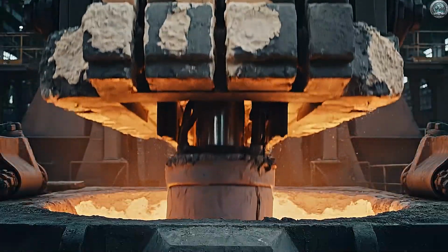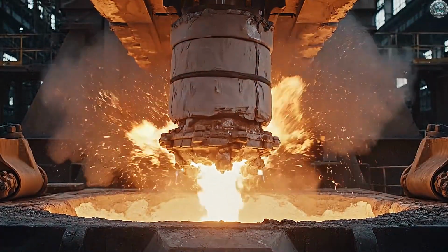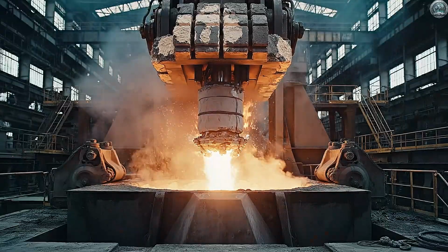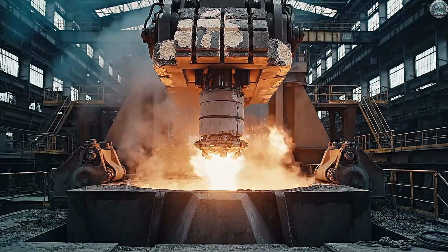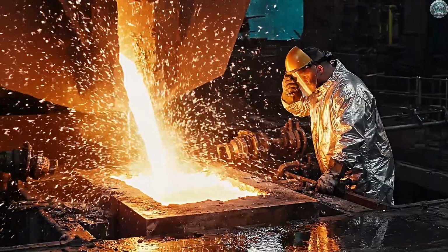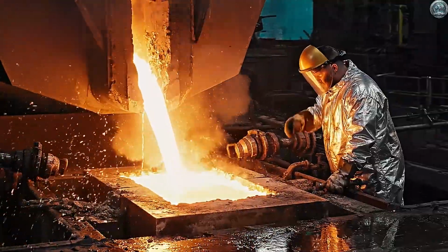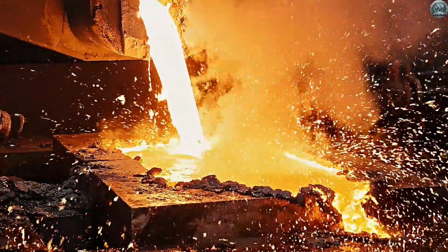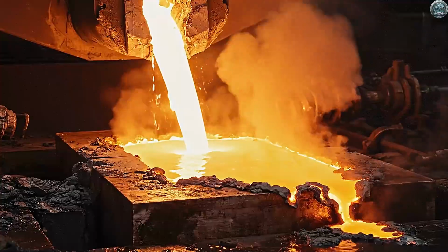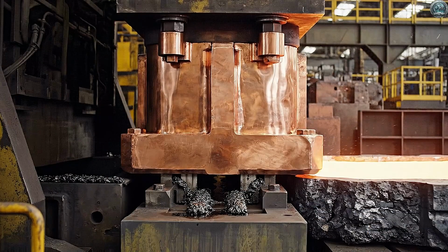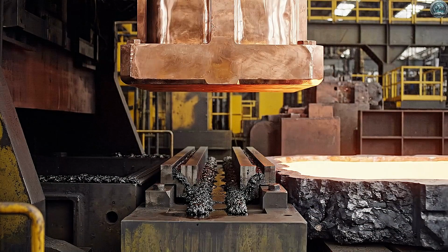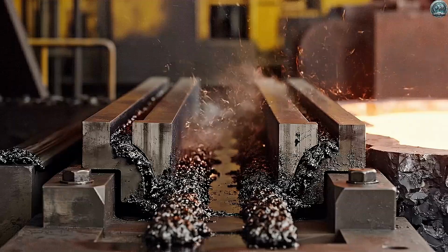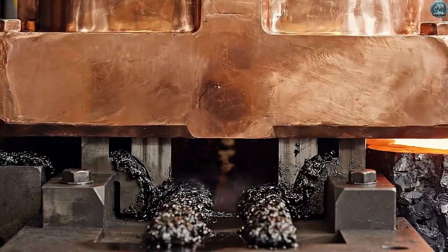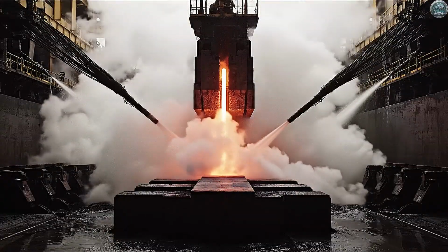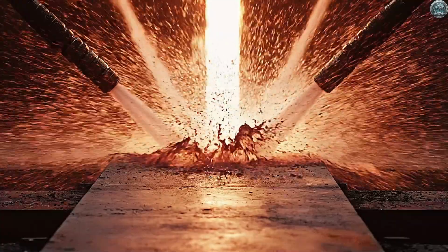Protected from the air, liquid steel flows invisibly into the tundish, a reservoir that feeds the molds. From the tundish, the steel is distributed into multiple strands, beginning its transition to solid form. Copper molds oscillate rapidly, a mechanical heartbeat that prevents the steel from sticking to the walls. High-pressure water sprays hit the emerging strand, freezing the shape instantly.